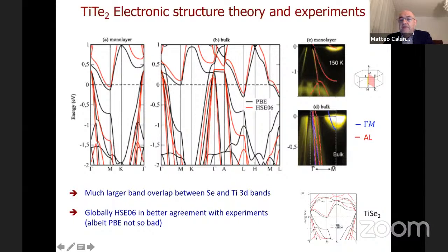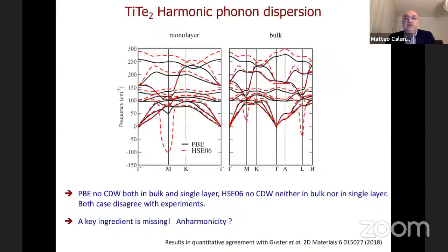If you look at the comparison with ARPES, you see HSE06 gives almost perfect agreement with ARPES for the slope of the band, the velocity, and the position of the bands. And I just recall what the situation was in titanium diselenide, in which the bands in HSE06 had no overlap between them. So HSE06 is good, almost perfect, PBE not so.